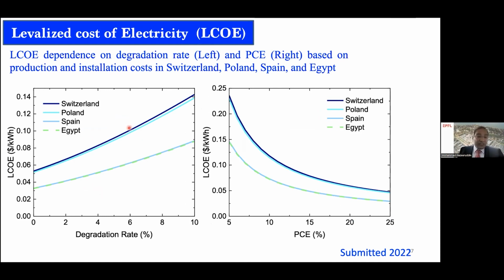Yes, on the left side is the degradation. Imagine our perovskite solar cells, the degradation is 2% per year, so the levelized cost of electricity goes slightly higher. If the degradation is 8%, this goes even higher, 12 cents per kilowatt hour. And if you look at the efficiency, since our small cells are giving 25% efficiency, the mini modules are between 22 and 23. So if you take this range, the levelized cost of electricity can be significantly lower.